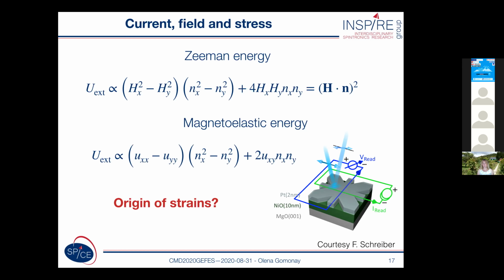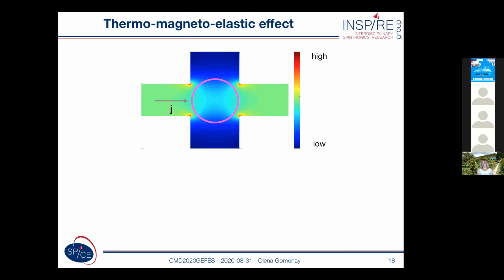we can look for the magnetoelastic mechanism in our case, but the question is, what is the origin of the strains? And if you look at the energy expression in the second line on this slide, you see that the strains which can remove degeneracy of the antiferromagnetic domains are shear strains. And what can be the origin of these shear strains when we try to switch the system electrically? For this, we should look at the real structure of the device, in which the antiferromagnetic layer is always clamped between the substrate and the platinum electrode. And the platinum electrode always has a very complicated geometry in order to induce reading, writing, and switching. So what happens in a real device? Current